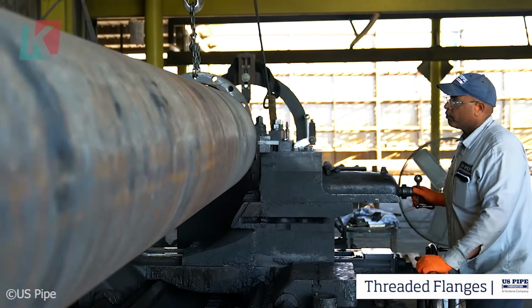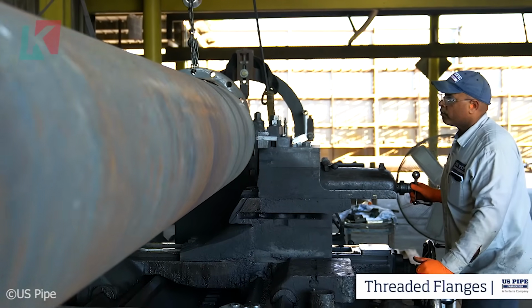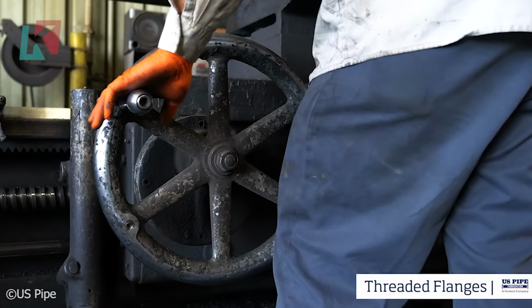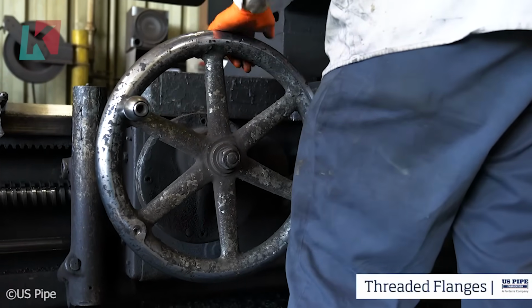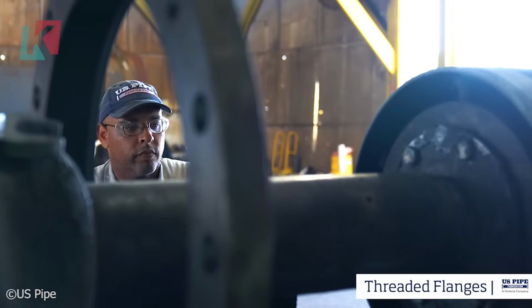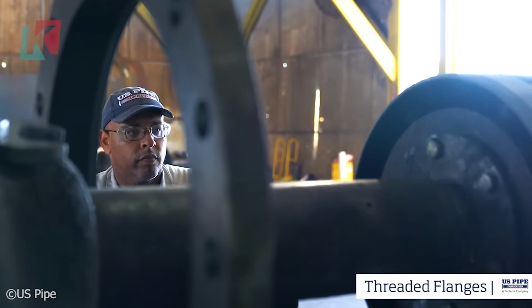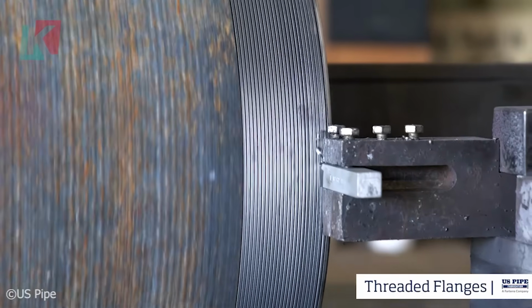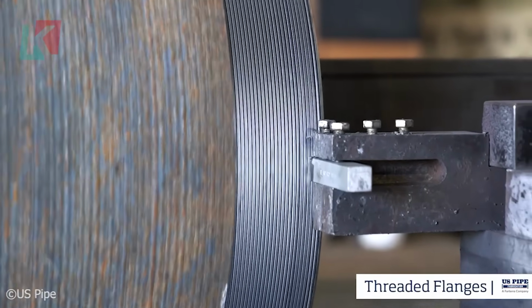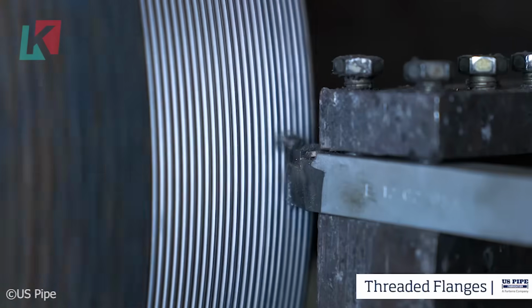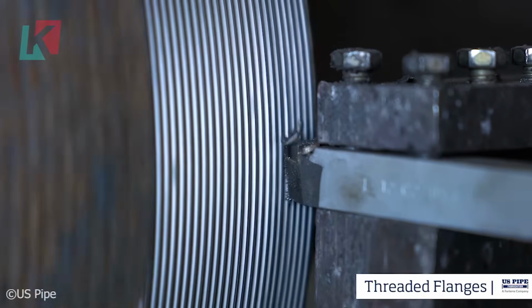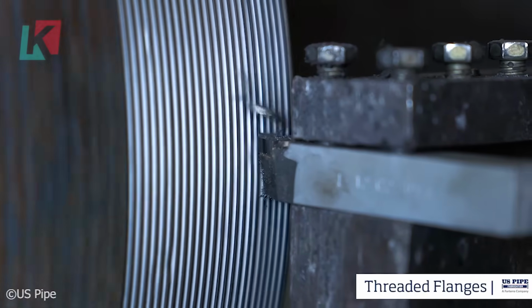The coating process you're witnessing is equally impressive. That's a specially formulated cement mortar lining being applied centrifugally. This isn't just protection. It's engineered to provide smooth flow characteristics that actually improve over time as the pipe is used. The exterior gets a zinc coating followed by an asphaltic seal coat, a 3-layer protection system that can last over 100 years underground.